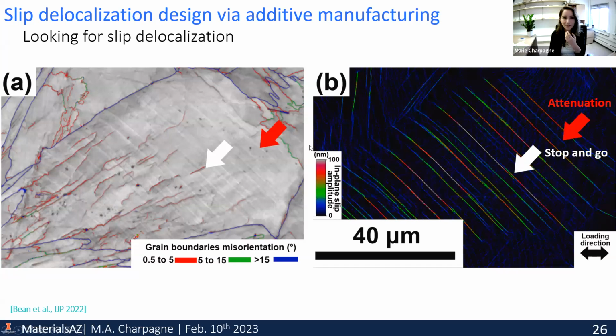We have not tested this one in fatigue because, well, anyone here who's working on additive manufacturing knows that there are much worse things in those additive manufactured materials, such as pores and cracks and smaller defects. But I believe that once we manage to minimize the amount of defects, these materials will actually be pretty good in fatigue.